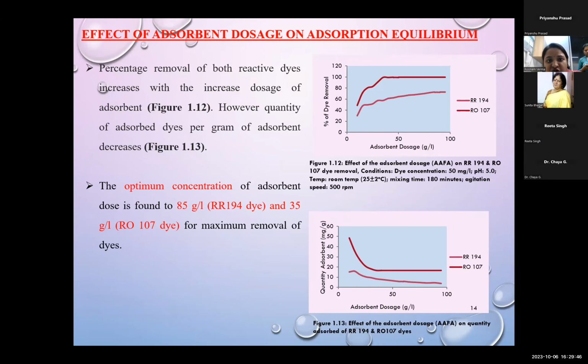Next is the effect of adsorbent dose on adsorption. From both the graphs, we can say that the percentage removal of both reactive dyes increases with increasing dose of adsorbent. However, the quantity of dye adsorbed per gram of adsorbent decreases, because the number of heterogeneous sites increases and the amount adsorbed per unit of adsorbent decreases. The optimum adsorbent dose was found to be 85 grams per liter for reactive red and 35 grams per liter for reactive orange dye for maximum removal.